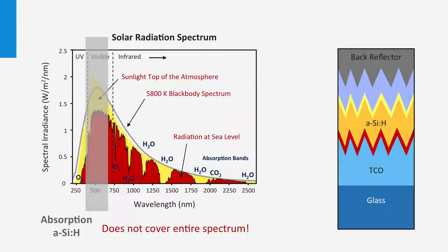The best open circuit voltages are in the order of 1 electron volt. With respect to a bandgap of 1.75 electron volt, the bandgap utilization is relatively low due to the high levels of Shockley-Read-Hall recombination and the relatively broad valence and conduction band tails. The best stabilized efficiency of a single junction solar cell is 10.1% obtained by the research lab of Oerlikon Solar, currently part of Tokyo Electron.